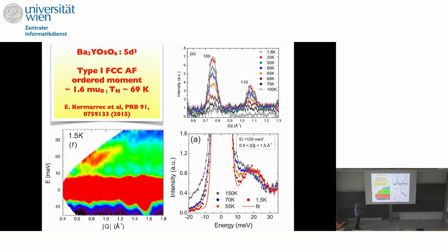But then the surprise came when we looked at the inelastic scattering in the same samples. And so this is time of flight inelastic scattering from this system. And so this is energy versus mod Q. If you look at the wave vectors where the Bragg peaks are, and just above them in energy, you can see that there's a clearly gapped excitation, and it's got a big gap, okay?